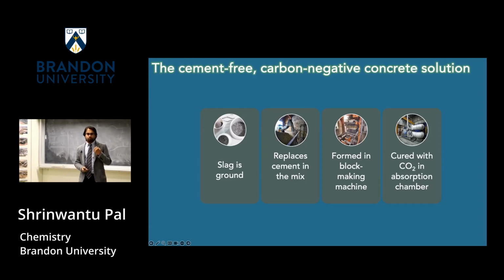Again, we solved the big issue here because previously they were trying with pressures that cannot be used without special permits. If you want to use, say, 4 megapascals of CO2 and you're starting to set up a company, the first question people will ask you is, is my CO2 tank going to explode? So one good thing that came out of this research was that the CO2 pressures we figured out were optimal are actually just slightly more than the ambient pressure of the atmosphere. So 1.2, 1.3 atmospheres. Then that block after curing is taken out.